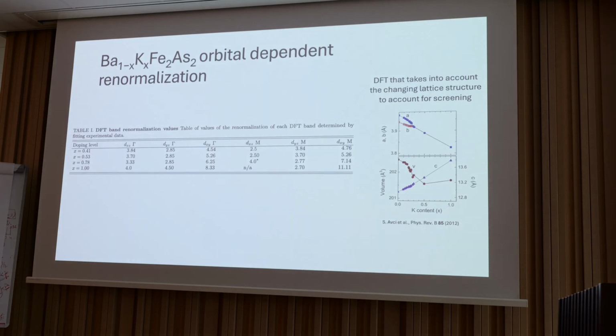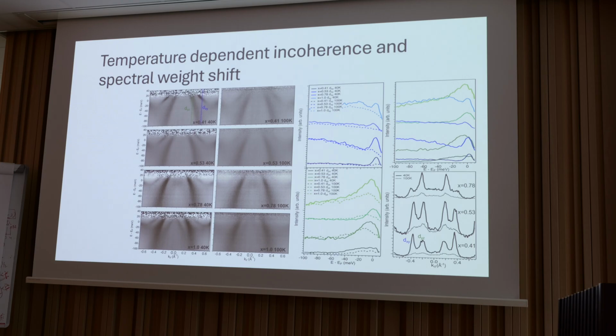So, back to our study. Our collaborators do DFT that takes into account the changing lattice structure to account for screening as well as this increased doping. When we compare that to our experimentally determined bands, we see a clear trend of an increase in the renormalization for the dxy band specifically as you increase hole doping. That is one piece of evidence for this increase of the Hund's coupling.